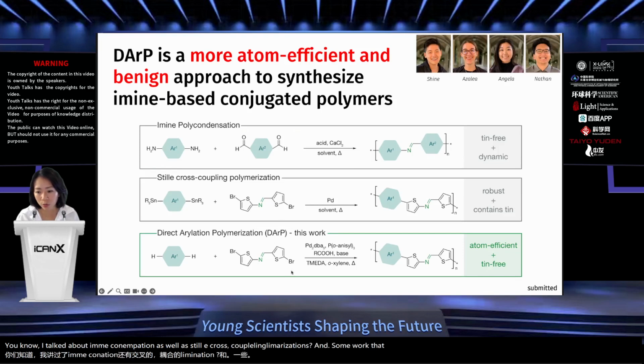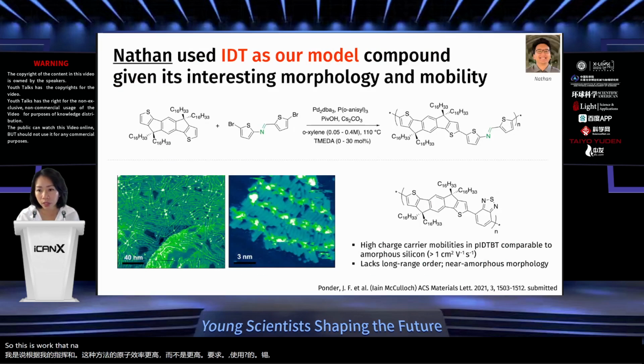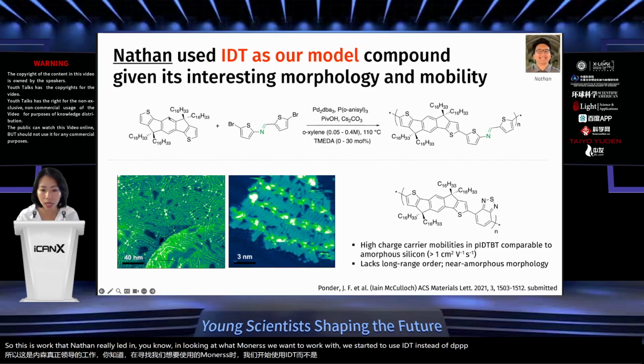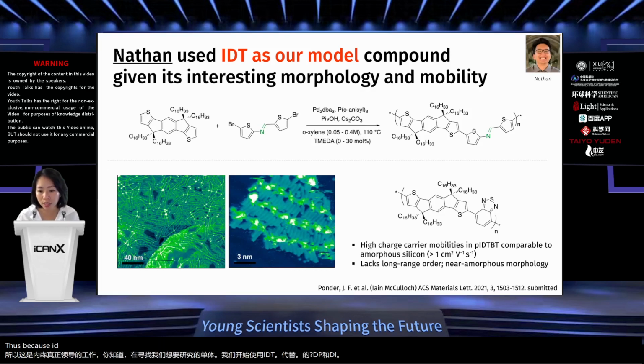And some work that we recently submitted is using direct arylation polymerization to prepare imine-based semiconductors. And this method is much more atom efficient, as well as it doesn't require the use of tin. So this is work that Nathan really led. And in looking at what monomers we want to work with, we started to use IDT instead of DPP or NDI. And that's because IDT has really high charge carrier mobilities that are comparable to amorphous silicon.